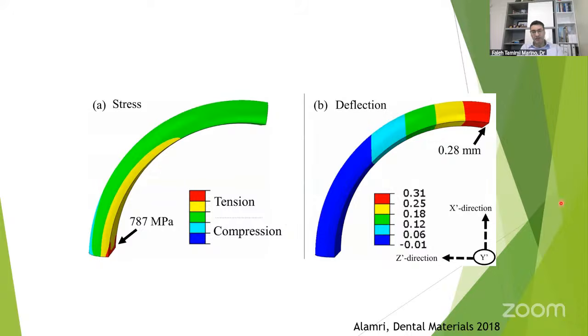This is a simulation in the computer of what happens to a clasp when you engage an undercut. This graph over here is showing deflection, how much it's bending. The tip is bending quite a bit because it's engaging the undercut every time it goes in and out, and this is a mechanical stress on the clasp. The area of the clasp that is engaging the minor connector is undergoing very, very high stress. So this is a simulation of a very simple clasp in the computer, and you can see that in this area here there is a lot of mechanical stress just by putting the clasp in and out.